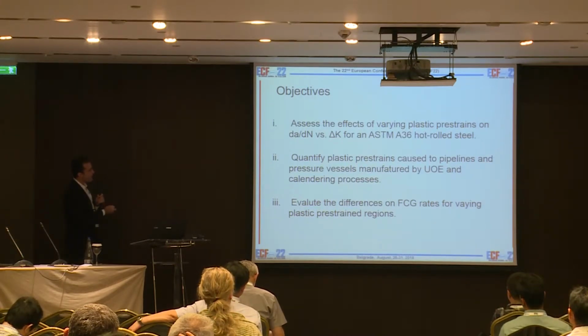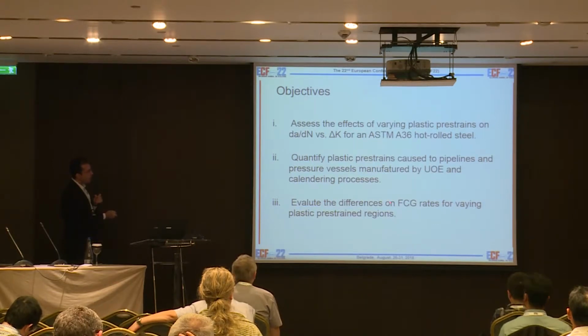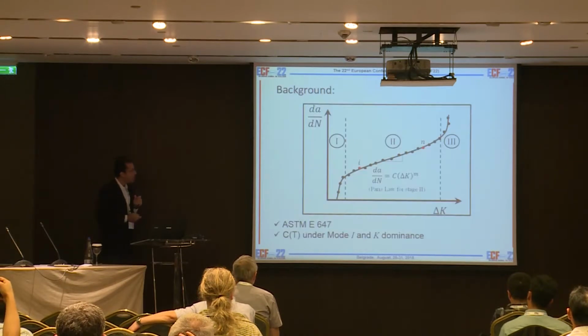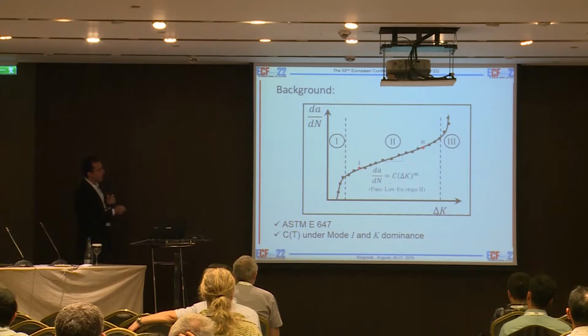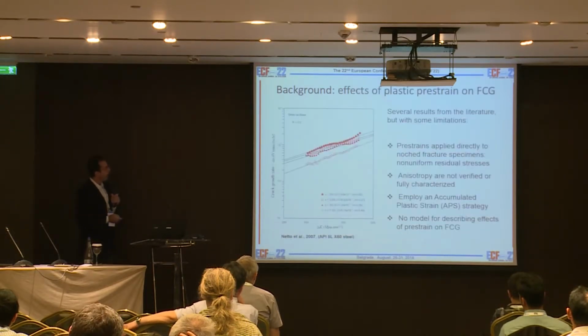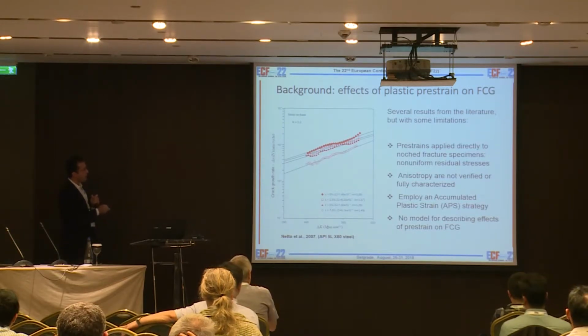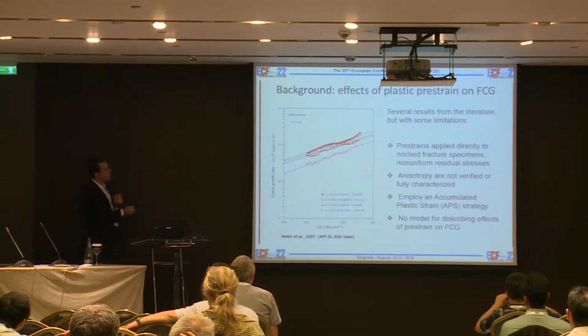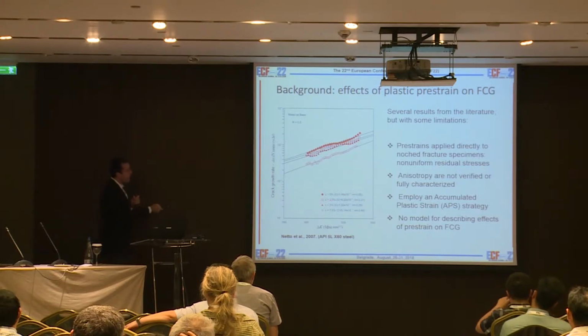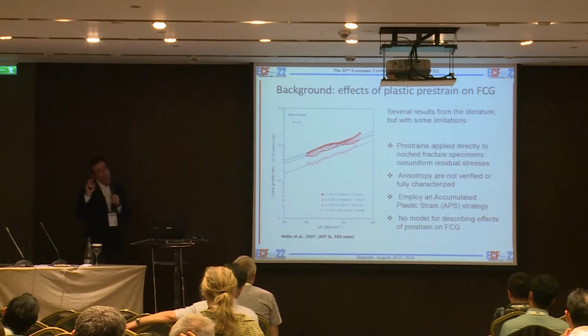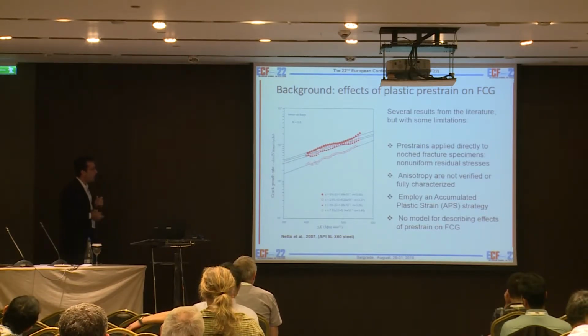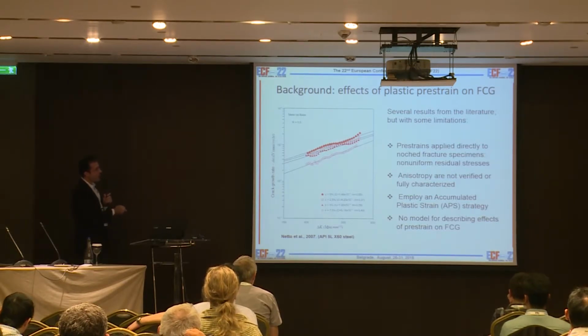Second, to quantify plastic prestrains caused by the processing methods, and evaluate the differences on fatigue crack growth rates for different regions in the components. So we use as a reference Paris law and conventional fatigue crack growth testing under ASTM E647 under mode 1 and K dominance. This is a result that is already published in the literature by Neto et al. 2007, just to show you the effects of increasing plastic prestrain on fatigue crack growth. The literature says that if you increase plastic prestrain, you reduce the da/dN, the crack growth rate. So in theory, it would be better to have more plastic prestrain if it's under control than having zero or opposite strain. This is just an example, but there are several limitations.